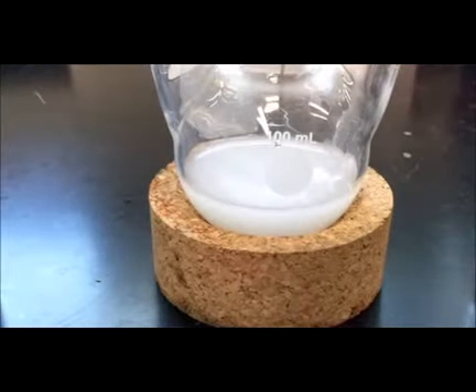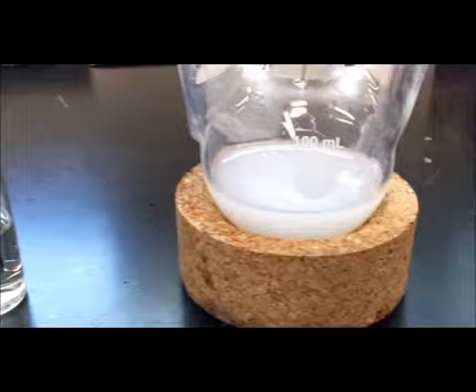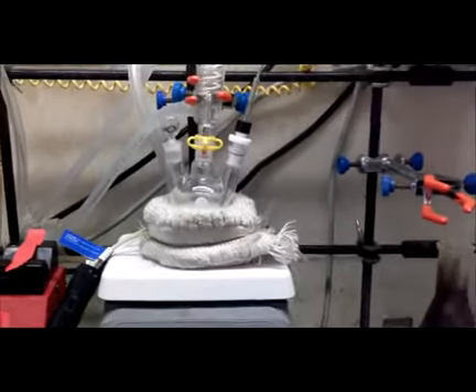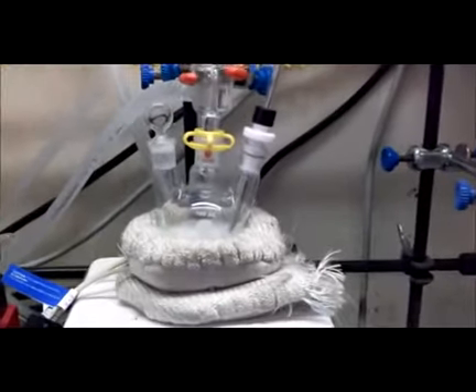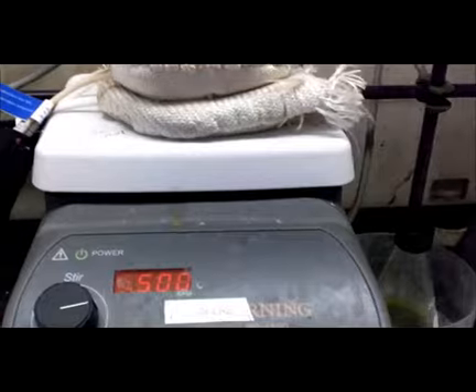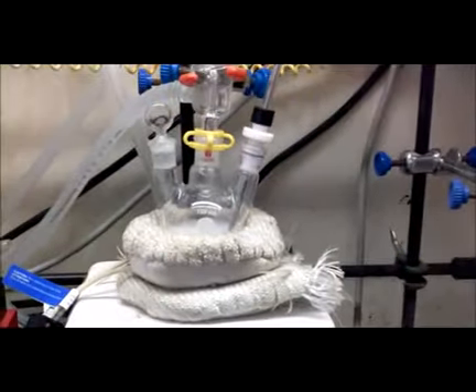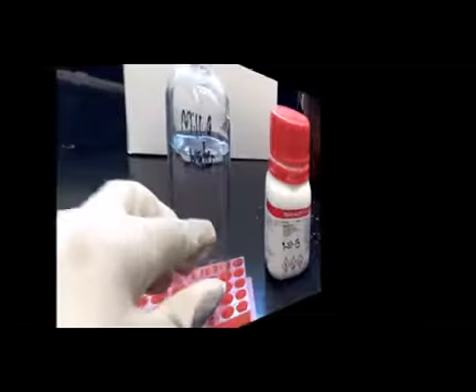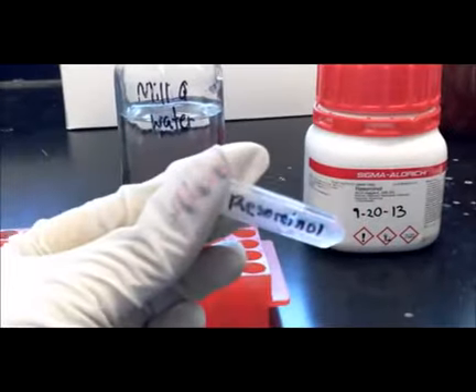After centrifuging and sonicating the lithium titanate with 29 milliliters of deionized water and putting it in the RBF, we measure out 0.1 milliliters of ammonia and add it to the RBF. We then add 1 milliliter of CTAB to the RBF. We then put the RBF in the reflux condenser and let it stir at 500 rpm and set it around 60 degrees Celsius. While the contents are heating, we make our 0.5 milliliter resorcinol solution.